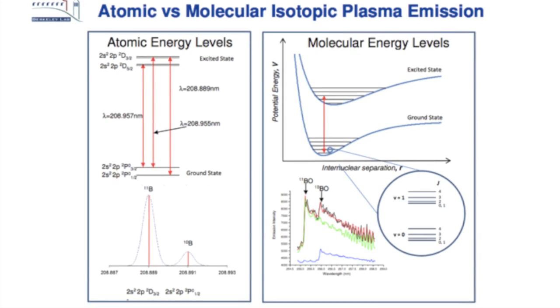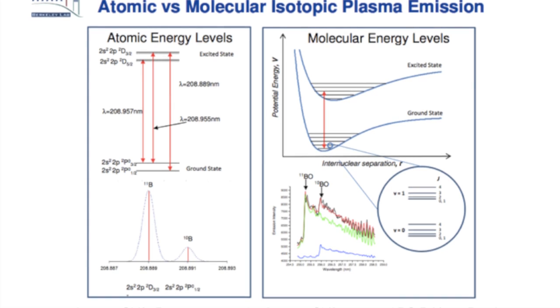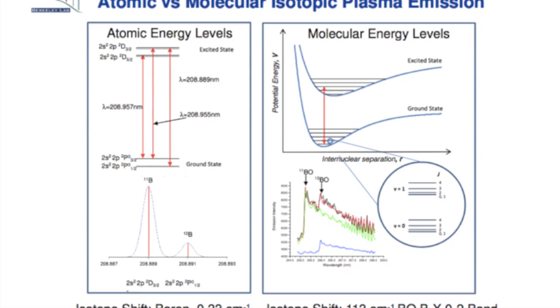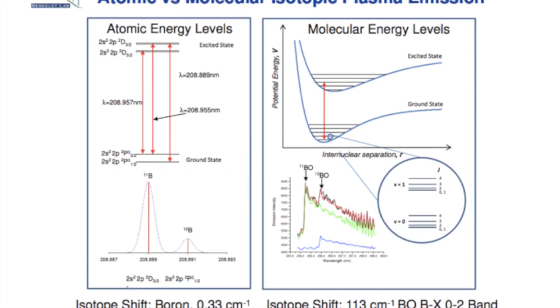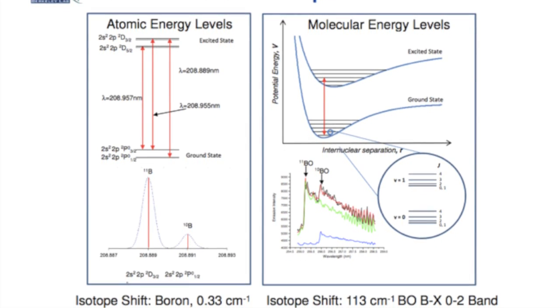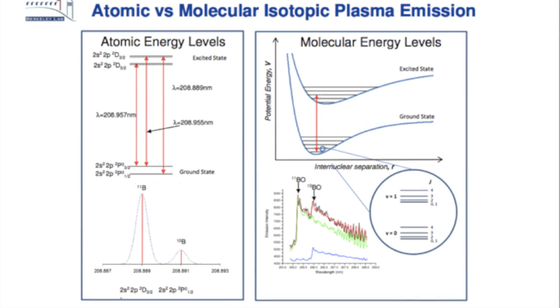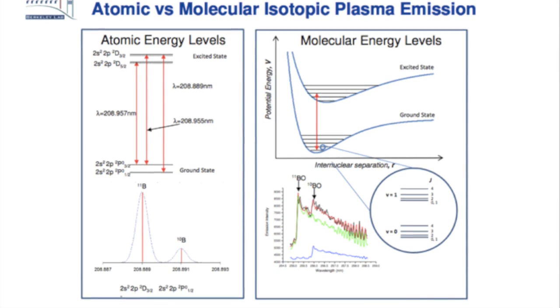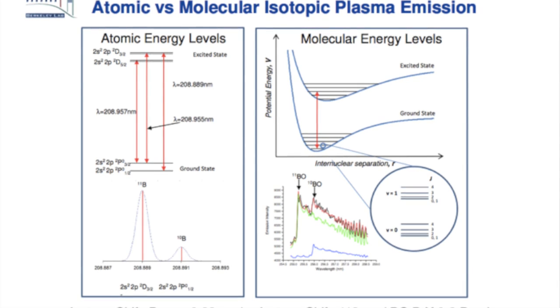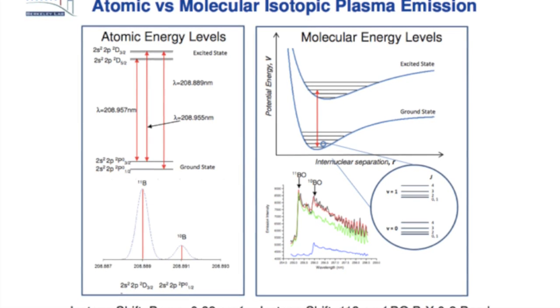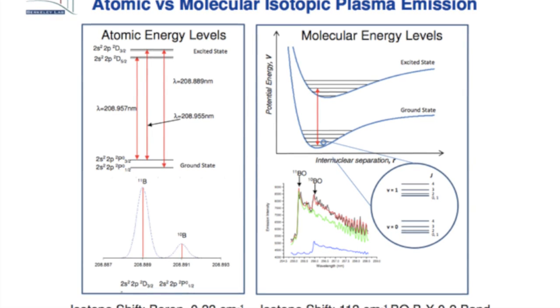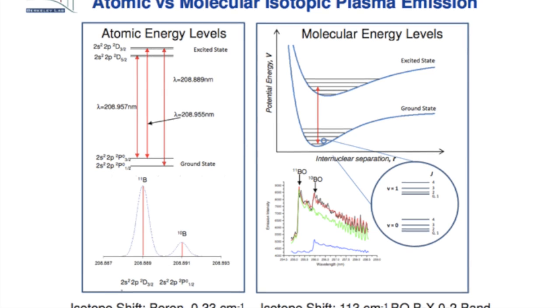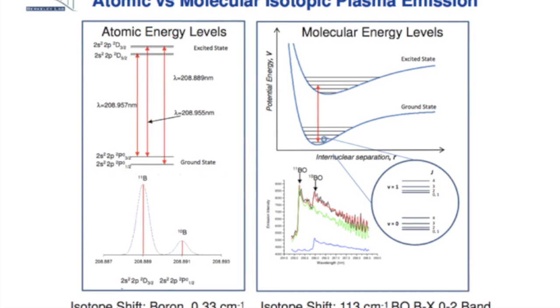So an atomic transition from a ground state to an excited state, you have very small shifting of the excited state due to mass differences of your element, so you get very, very small isotope splitting. That's what I talked about earlier with that chart from Livermore. So for boron 10, boron 11, I'm going to go back and forth between wave numbers and wavelength, so I apologize for that. I should try to be more consistent. Anyway, 0.33 wave numbers, I think, is only on the order of a couple picometers. And we'll see something different on some other slide.